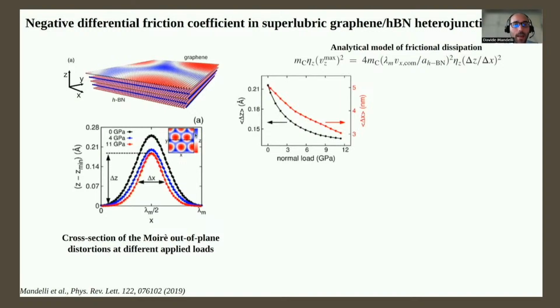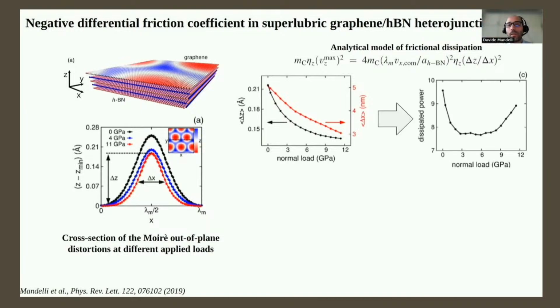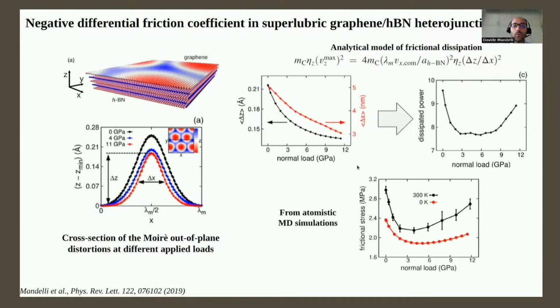This would lead to a counterintuitive effect where friction would reduce upon increasing the external normal load. And this is actually what we observed, both in a minimalistic analytical model that we were able to build and also in full atomistic molecular dynamics simulation.